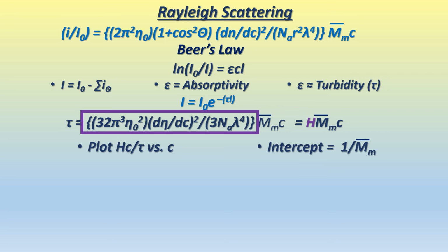Light scattering is an incredibly accurate and also a very meticulous process. The solvent has to be perfectly clean, perfectly pure, and the sample has to be dissolved so that the scattering centers are actually single polymer chains and not agglomerations of polymers. However, once these terms are met, the method is very straightforward and gives a very accurate result.